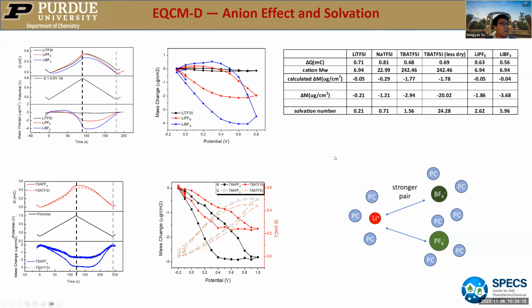And another effect is for the anion. I compared lithium TFSI, lithium PF6, and lithium BF4. They have similar charge capacity, but they also have different mass transport. We can say lithium PF6 and lithium BF4 are heavier than lithium TFSI, which is understandable because we assume TFSI participates in the process, but PF6 and BF4 may not.